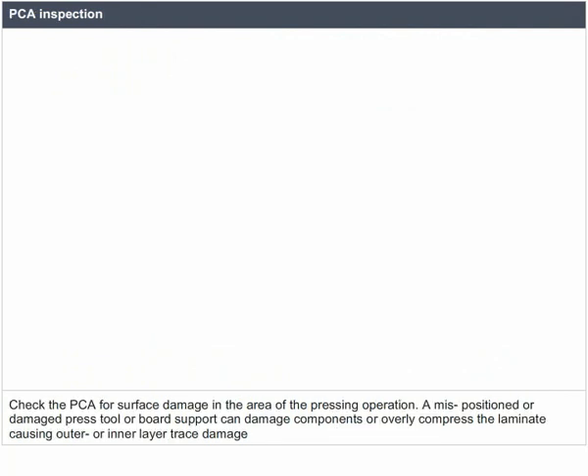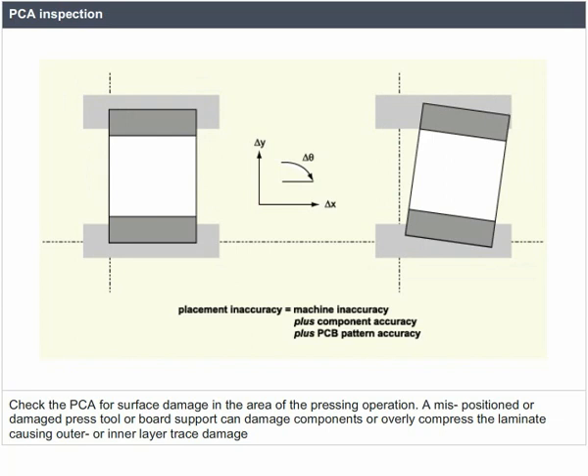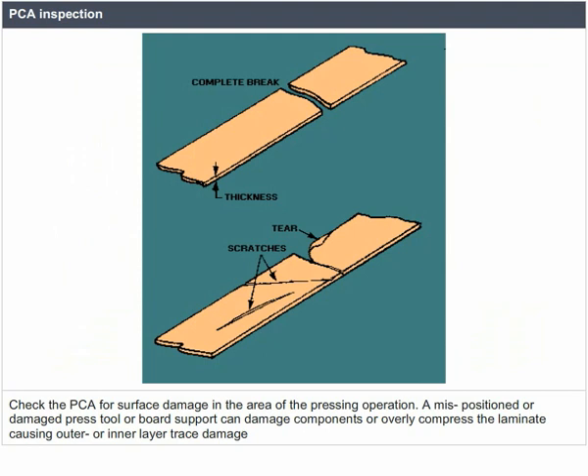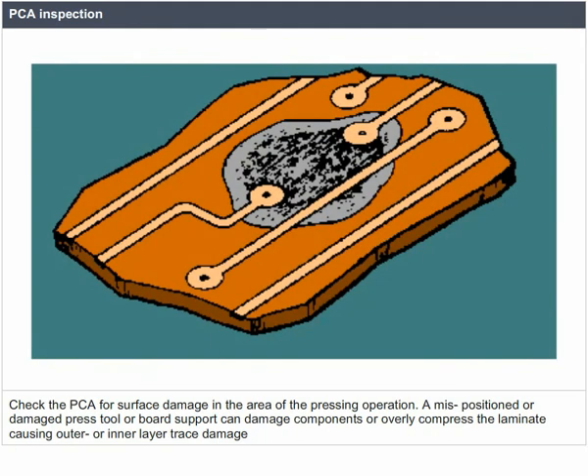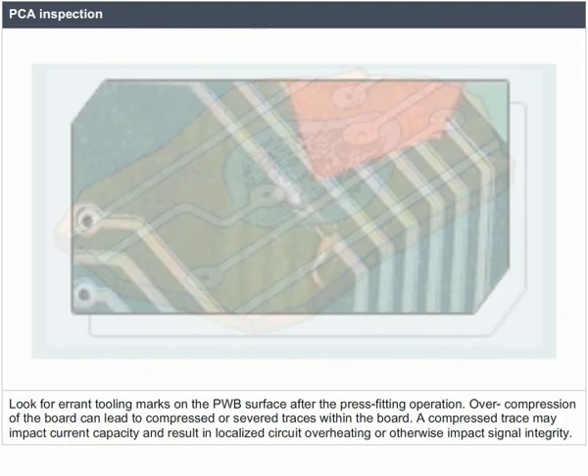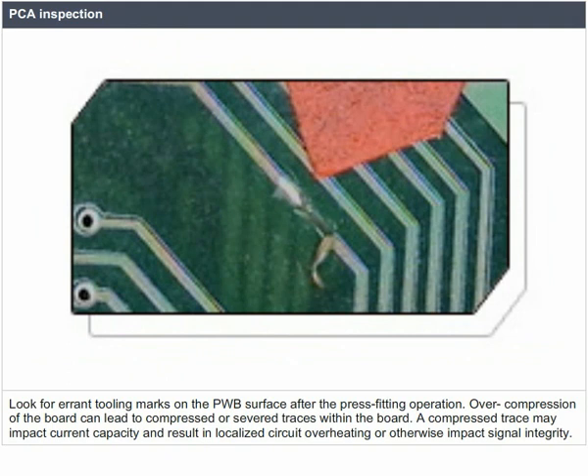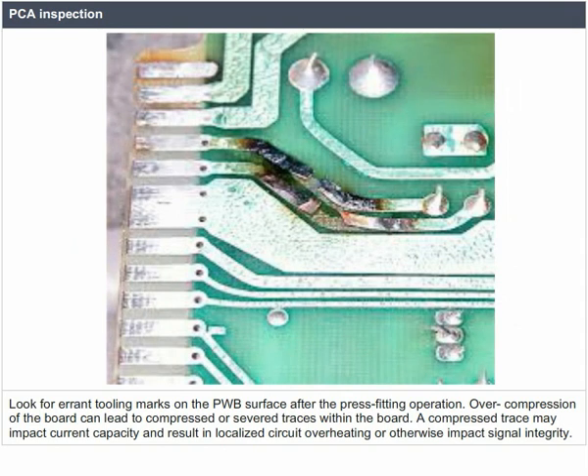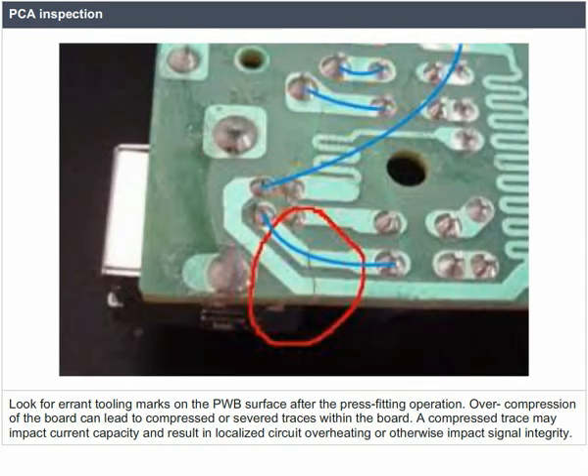PCA inspection. Check the PCA for surface damage in the area of the pressing operation. A mispositioned or damaged press tool or board support can damage components or overly compress the laminate, causing outer or inner layer trace damage. Look for errant tooling marks on the PWB surface after the press fitting operation. Overcompression of the board can lead to compressed or severed traces within the board. A compressed trace may impact current capacity and result in localized circuit overheating or otherwise impact signal integrity.